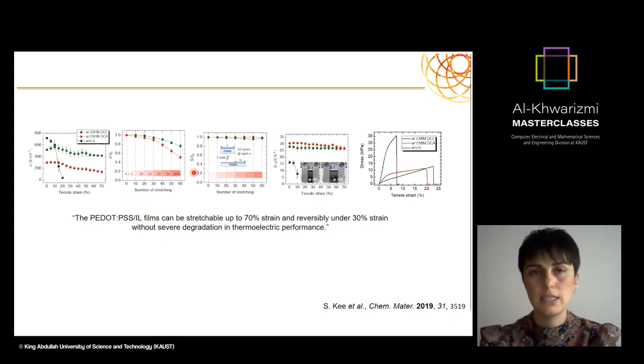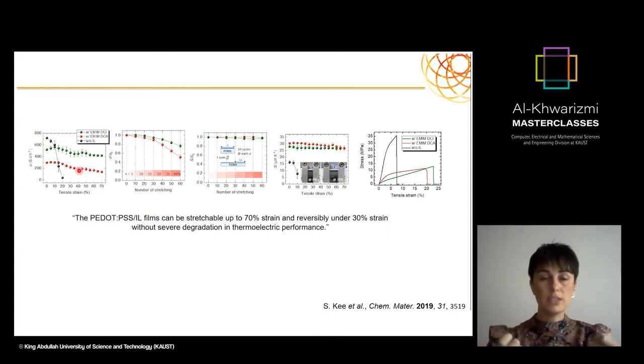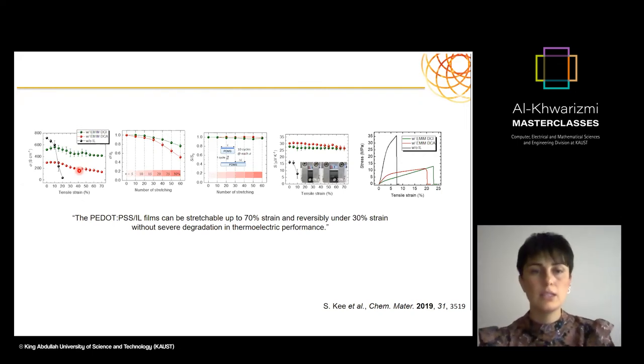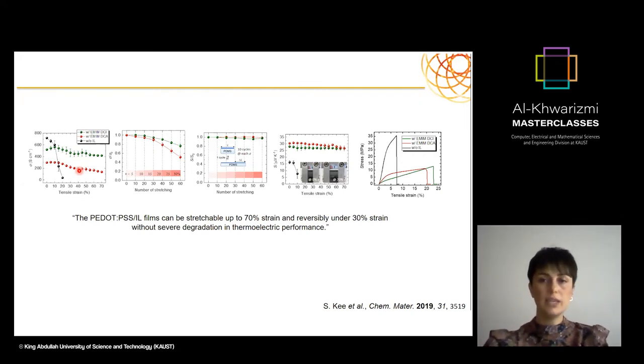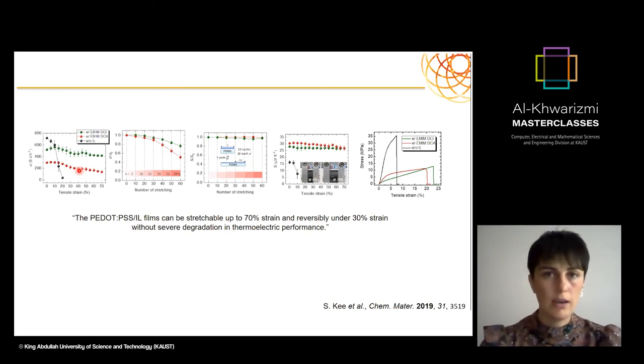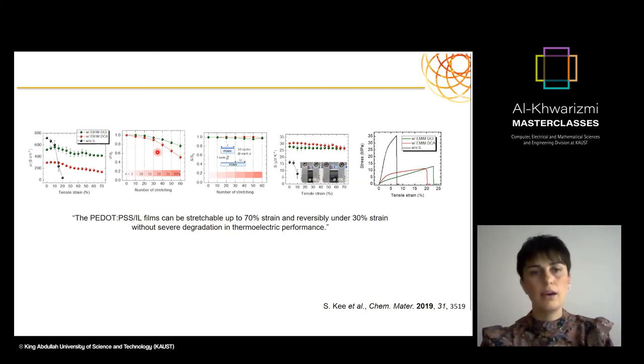And in the end, it's ZT, the unitless figure of merit. So what you can see here, the conductivity of the PEDOT itself as a function of different tensile strain goes really, really low after 20%. However, using the ionic liquids, we were able to keep this conductivity up to 70% strain and stretchability with these devices, because if we want to use them in body applications, you need to be able to stretch to a certain extent. And then we also did different tests with the number of stretchings, etc. And then we have seen up to 50 cycles relatively okay conductivity scales.